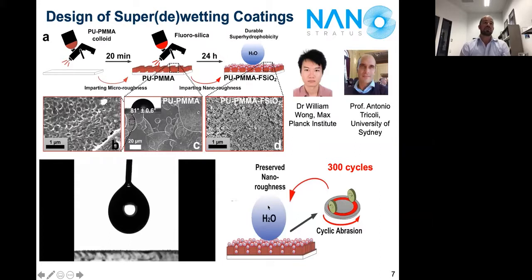But what we managed to do is we created an ultra durable super hydrophobic coating. So you can imagine that these coatings basically resist water. So you can use them as anti-fogging coatings for glasses, buildings like your windows, so you don't need to actually clean your windows and things like that. They're sort of self-cleaning and stop any accumulation of dirt and water on the surfaces. And I have a movie of that here.